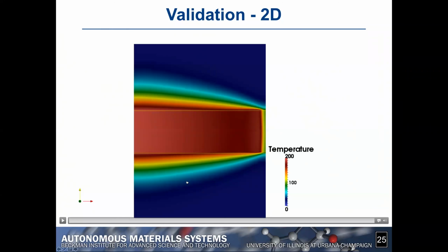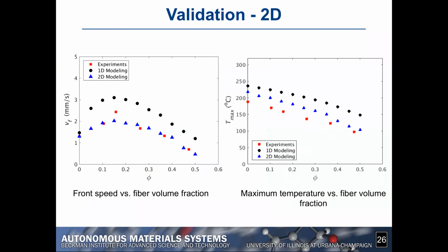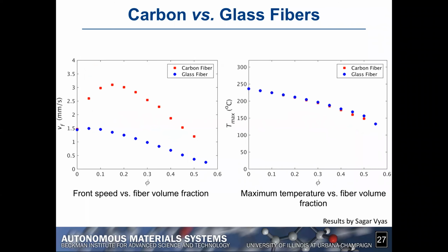And so if we actually look at these results and compare that to the experiments now, we can see that these 2D results capture the experiments much more closely, especially with regards to the speed of the front, a bit less in terms of the maximum temperature. We still overpredicted a little bit, and we believe that the reason for it is that the location of the thermocouples that were used in the experiment is actually closer to the interface between the support and the composite layer.